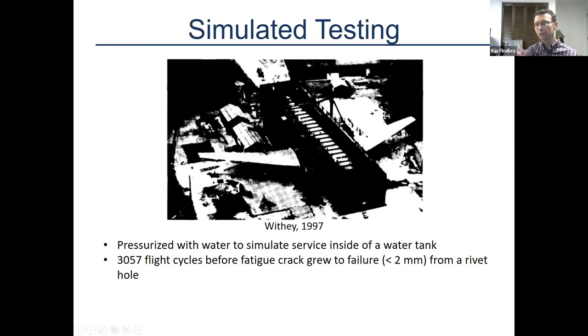So they actually did some pre-testing to make sure they thought that the plane could withstand the loads it would experience in the air, but that wasn't quite sufficient. So after the plane failed, they went back and they tested other planes to see if they could simulate what would happen over a certain number of cycles. And they did it with water.